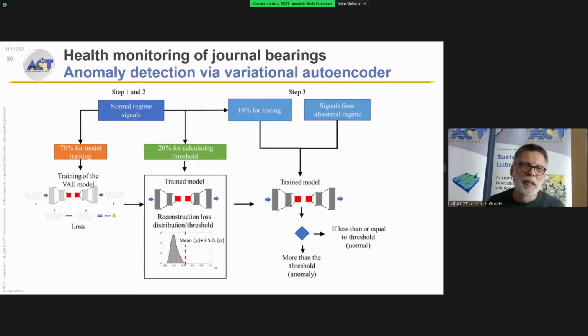Let's say that the anomaly detection with a variational autoencoder will work after the following scheme. You have a variational autoencoder which consists of a layered network here, a convolutional neural network, and we took data from the normal regime signals, split it into 70% training data and 20% for calculating a threshold, which would say later on if the state is still normal or not. Then we took 10% for testing and mixed them together with signals from the abnormal regime to see if the algorithm can really discern between normal and abnormal regime.